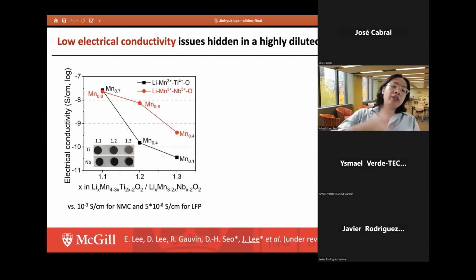And what we found is that the electric conductivity is on the order of 10 to the negative 7 or 10 to the negative 10 Siemens per centimeter, which is much lower compared to the value from the NMC (nickel manganese cobalt) type layered cathode, which is around 10 to the negative 3 Siemens per centimeter, or even poorer than lithium iron phosphate, which is another cathode material known to be a poor conductor.